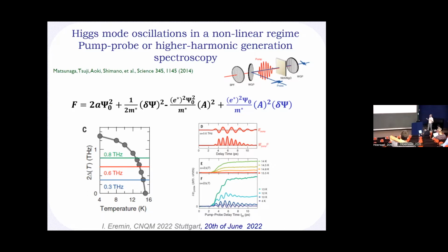For example, one way you can do pump probe spectroscopy is shown here, in a typical conventional superconductor, niobium nitride, where you apply a multi-cycle pulse and probe higher harmonic generation. You basically see a response connected to 2 times the superconducting gap, which you can very nicely see in the experiment by looking at the Fourier transform of the transmitted electromagnetic wave. The third harmonic generation looks like a signature of the coupling between the electromagnetic wave and the amplitude mode, which is the Higgs mode.